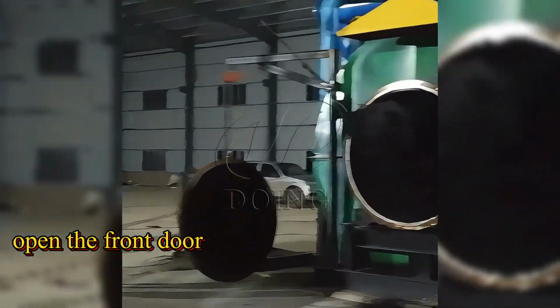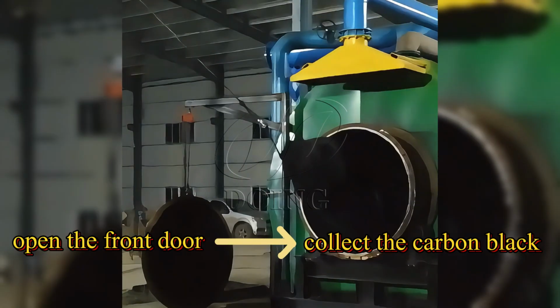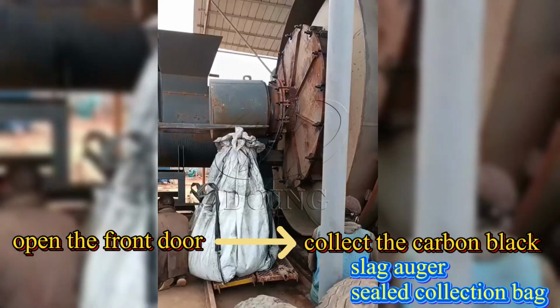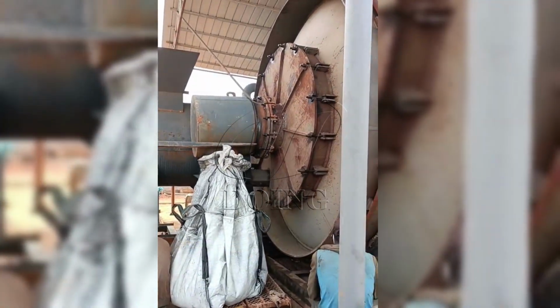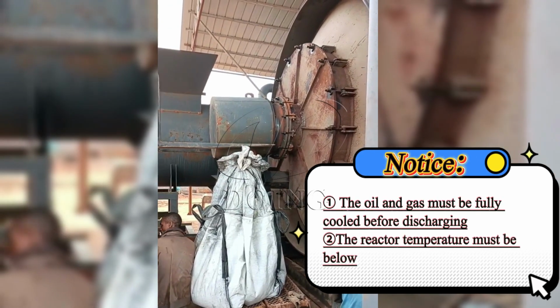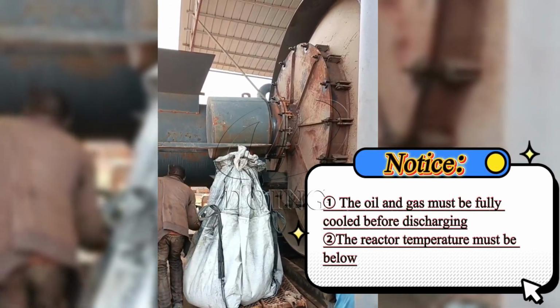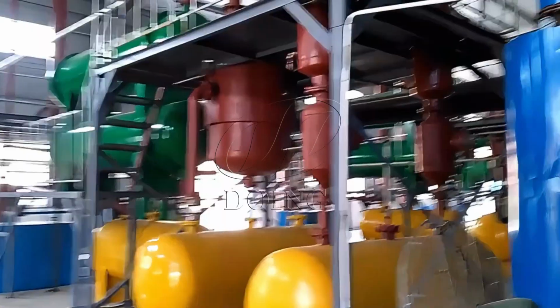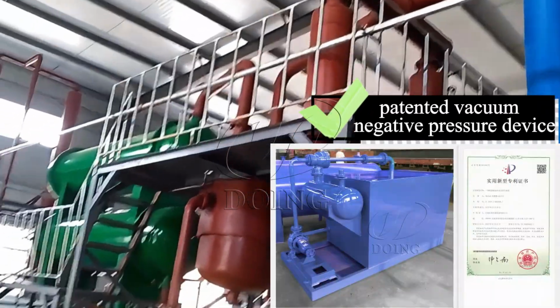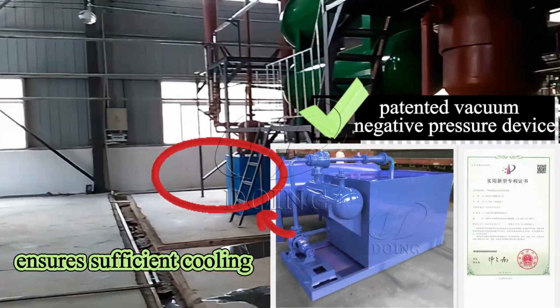Open the front door of the pyrolysis reactor and collect the carbon black using a slag auger or a sealed collection bag. However, before discharging, the oil and gas must be fully cooled, and the reactor temperature must be below 50. Our patented vacuum negative pressure device ensures sufficient cooling of the oil and gas.